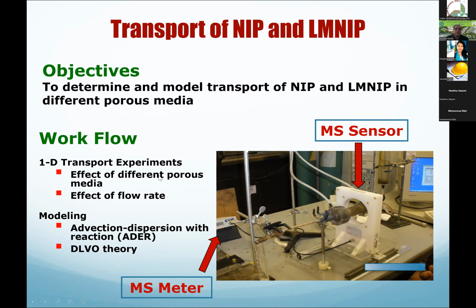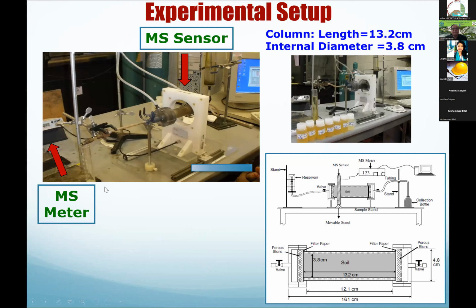So we did these experiments to look at the effect of porous media. The sand is not uniform, right? You may have fine sand, medium sand, coarse sand, well-graded sand. That will affect the transport of the nanoiron particles. We wanted to look at the porous media, even though it's sand, but different types of sand. And then the effect of flow rate: could you have higher flow rate or low flow rate? And then we wanted to do the modeling to predict that transport using the advection dispersion equation and DLVO theory. So this is the schematic.